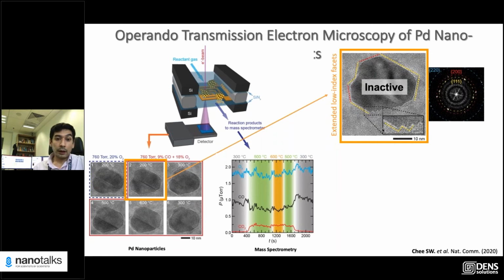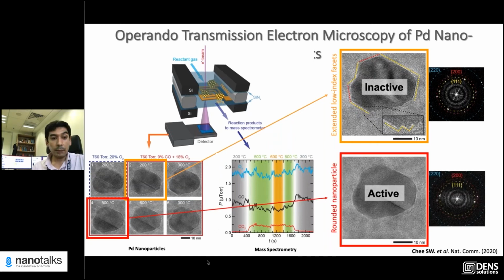Well, but nothing happens at 300 degrees or 200 degrees, right? So no reaction is going on. There is no CO2 being produced. And we slowly increase the temperature. And when the temperature reaches 500 degrees, we see the CO2 production. As we see the CO2 production, we can currently see how the active nanoparticle looks like, right? So the active nanoparticle is distinctly different from this one because it has all rounded faces, right?